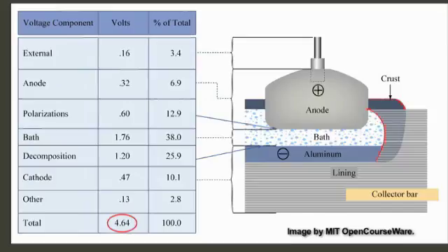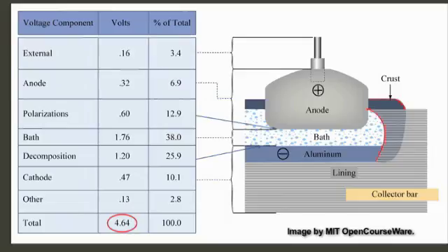What I want to do is, last day I talked about magnesium. Today I want to talk about aluminum. And it is also made in an electrochemical process. Well, in this case, the electrodes are horizontal. We feed aluminum oxide in and we pass current, and huge currents. This thing typically runs at 400,000 amperes and about 4 volts.